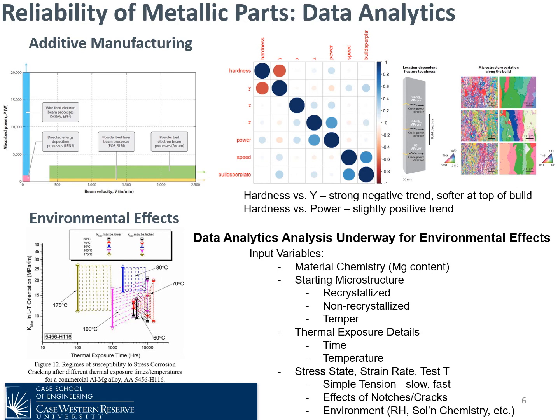On the environmental effects side, there's lots of variables here. As I showed before, when we expose these in the laboratory, we get different regimes where the material will crack. And so this is an ongoing student's project where he's looking at data analytics analysis for environmental effects on this material. So the input variables here are the material chemistry, magnesium content. What's the starting microstructure look like? What are the thermal exposure details, time and temperature? And then how does stress state, strain rate, and test temperature affect this?